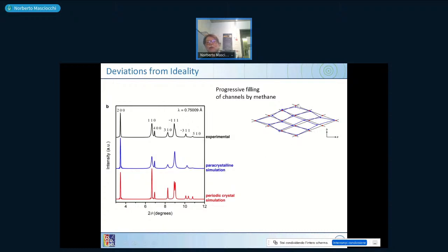So if you take the original mesh, which was this kind of rhombus with all the distances, because you are filling these chains by pumping in gas, in this case methane, these chains try to enlarge, but the distances between the atoms are fixed because these MOFs have linkers which are fixed in length. So what you can do is change all this net by shifting the atoms in a way that the distances between the atoms are kept constant. So these are not random shifts, because in a random shift you may have some atoms which go farther away, some which go closer, but the distance between these red atoms is maintained at the expense of different angles, which are not anymore the old ones.